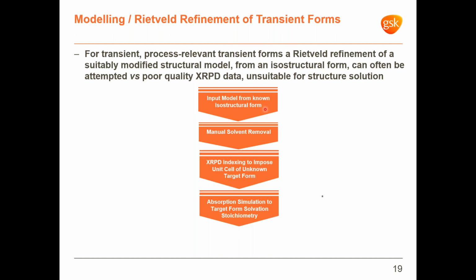We can then simulate the absorption of solvent molecules in the framework, aiming at the solvent loading suggested by experimental evidence such as GVS and consistent with the estimated void space. And we can finally refine the obtained model against the XRPD pattern. Typically, this would be a low resolution one. In these cases, data quality would not usually support the full Rietveld refinement, but an energy function in the form of force fields can be used as a restraint to better control the free refinement against XRPD data.